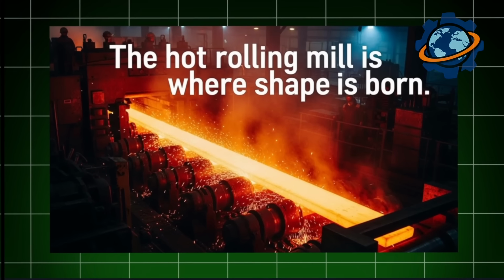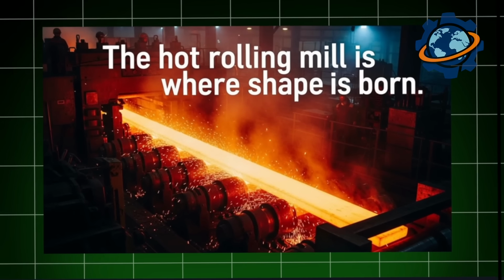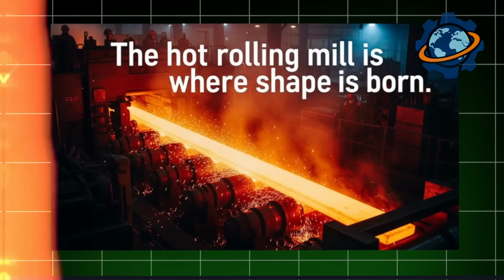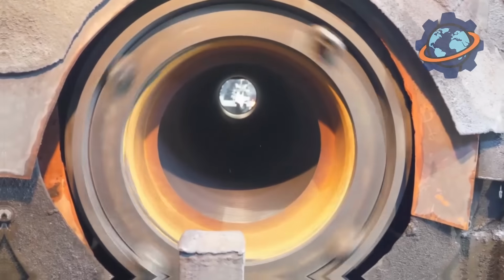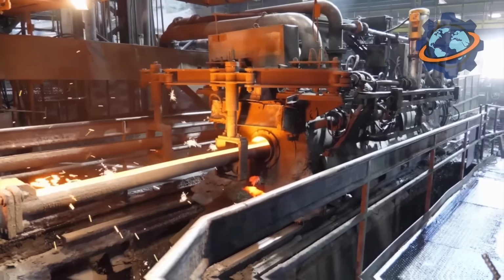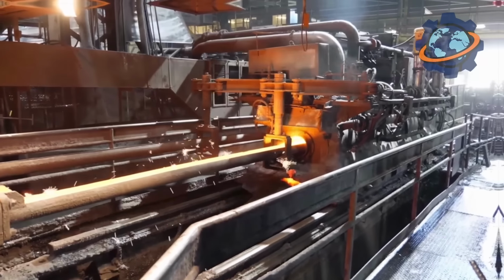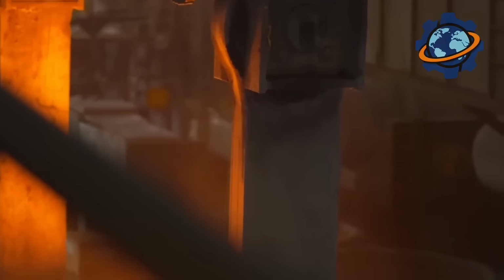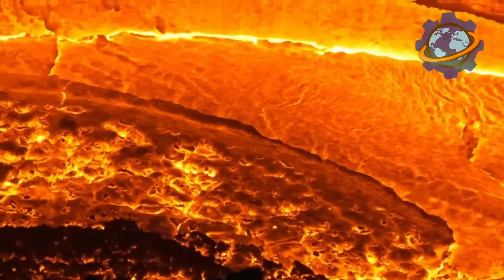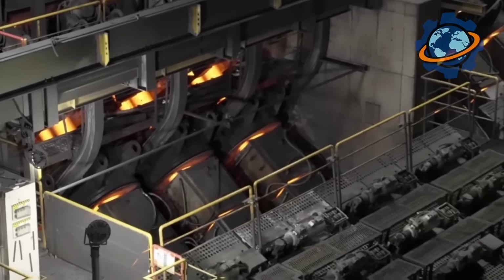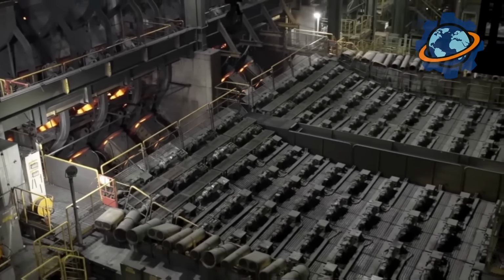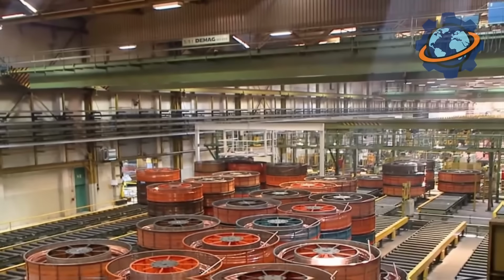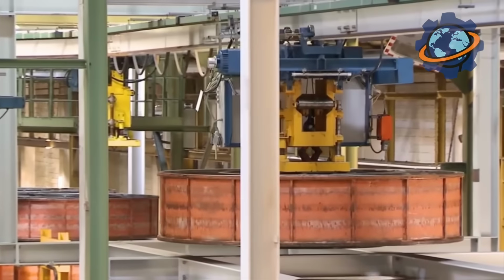The hot rolling mill is where shape is born. The continuous cast billet, still glowing red at 2,000 degrees, enters the roughing mill. Giant rollers, each weighing 30 tons, squeeze the steel, reducing thickness while increasing length. The transformation is violent. 8-inch square becomes flat bar 6 feet wide and 1/4 inch thick in 7 passes through successive roller stands. Watch the mill operation.